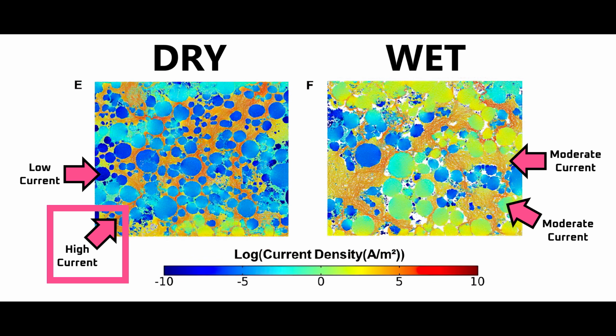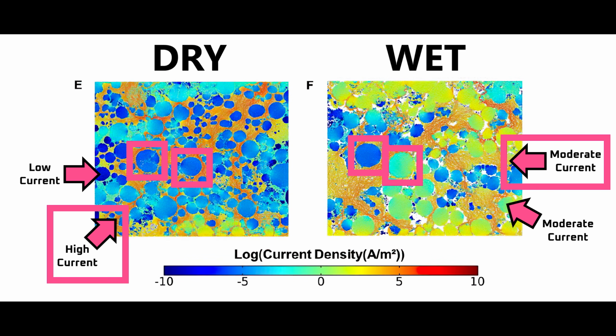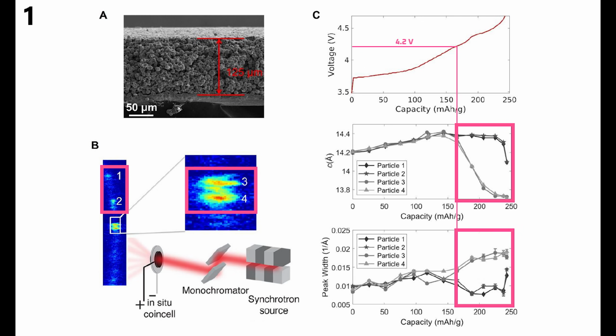Additionally, the carbon binder matrix contains more yellow and green than image E, so it's carrying less current. What all this means is that the dry-coated cathode directs most current through the preferred low-resistance carbon binder matrix, and any current that flows through the cathode particles does so relatively evenly. That's as opposed to the wet-coated cathode, where the carbon binder matrix is electronically fragmented, forcing uneven and heavy use of the inefficient cathode particles as a current path, which of course leads to the variations in voltage and therefore degradation that we saw earlier in the video.